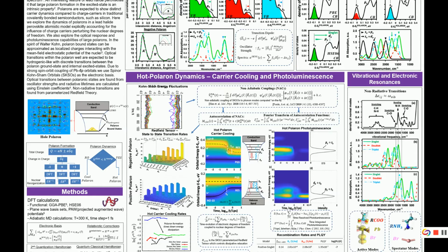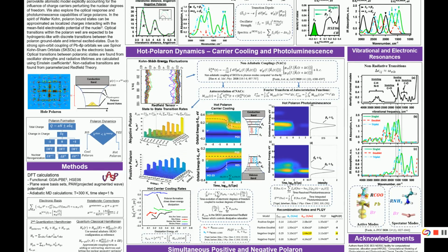So the main distinction that I see is for our negative polaron: there's a two order of magnitude difference between these two transitions. The way I rationalize the difference is that the carboxylates chemically bond to the system, so they provide active modes of vibration, which directly contribute to the non-adiabatic couplings. Whereas the NH bending modes from the ammonia don't provide electronic density to the surface. They're more spectator modes, so they don't actually provide any vibrational pathways to release energy. So this excited state has a longer lifetime due to a detuning from other vibrational modes.